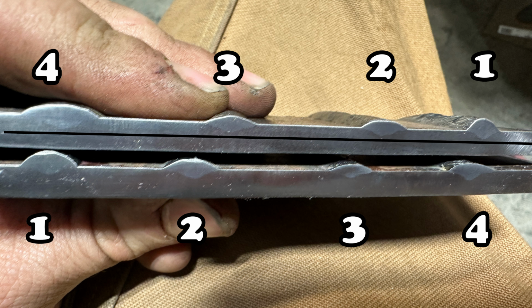But when we look at the top plate, which is mine, the depth of penetration on all of them is virtually the same. I would say 1 and 4 are the best, then 2, then 3, or somewhere around there. But it's not like night and day different. We can tell that the plate was preheated for 2, 3, and 4 simply because the welds are flatter and wider, but that's it. There is no increase in penetration.